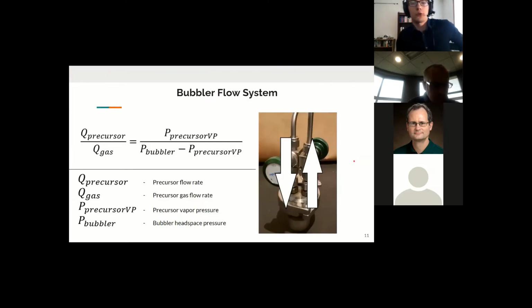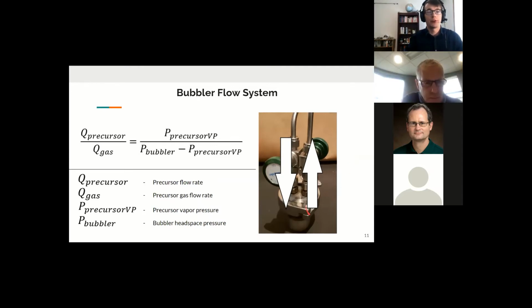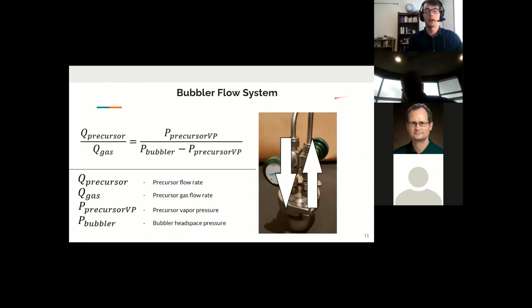An example of a liquid bubbler can be seen in this figure. The bubbler contains the liquid precursor in the bottom, into which the input gas bubbles. So a bubble starts at the bottom of the liquid, and as it rises, molecules of the liquid precursor enter the gaseous bubble, which vaporizes the precursor. The constant flow of gas into the bubbler pushes precursor vapors downstream and into the plasma reactor.